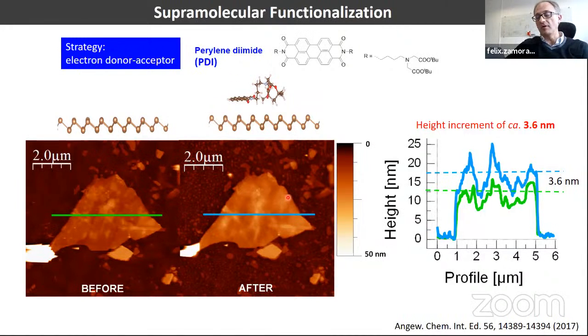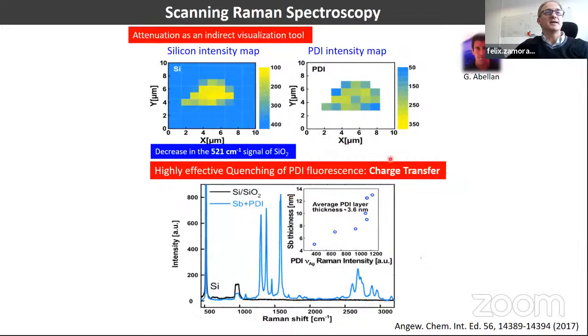So probably the molecule, we hope. And this is what we try to characterize using, for instance, scanning Raman spectroscopy, and this is the result. Here we have just the antimony layer. So we map here only the peaks corresponding to the signal of silicon oxide. And as we have the antimony layer on top of the silicon oxide, here we observe a decrease in this signal, of course, corresponding to the location of our antimony layer.